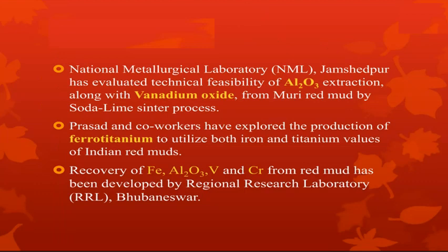Here are some processes developed in India for metallurgy. First one is National Metallurgical Laboratory, Jamshedpur, has evaluated technical feasibility of Al2O3 extraction along with vanadium oxide from Muri red mud by soda lime sinter process. Second one, Prasad and co-workers have explored the production of ferrotitanium to utilize both iron and titanium values of Indian red mud. Third one is recovery of Fe, Al2O3, V and Cr from red mud has been developed by Regional Research Laboratory in Bhubaneswar.